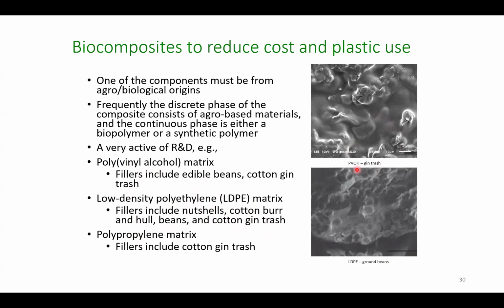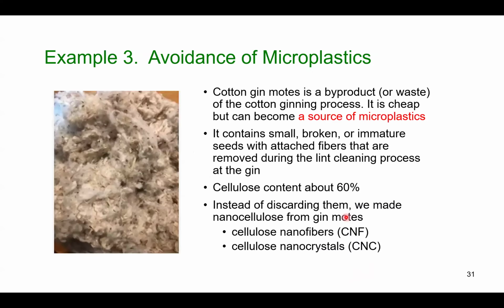So here is polyvinyl alcohol with gin trash, an SEM picture. Both of them are hydrophilic, so you can see that they adhere fairly well, the filler and the polymer matrix. And this is low-density polyethylene with beans. Now, the low-density polyethylene is not hydrophilic. Beans are. So you can see that the materials don't adhere as well, but we can make a blend accordingly.